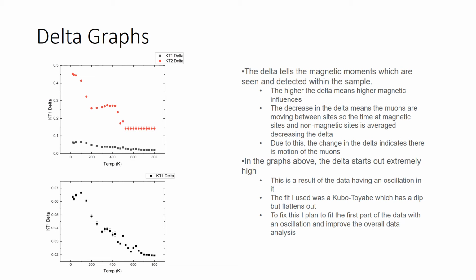Along with the amplitude versus temperature graphs, the fits also produced delta graphs, and the delta tells the magnetic moments which are seen and detected within the sample, which is done using the spin polarization, as previously mentioned, with the zero field runs. The higher the delta is, the higher the magnetic moments or magnetic influences in the actual sample.